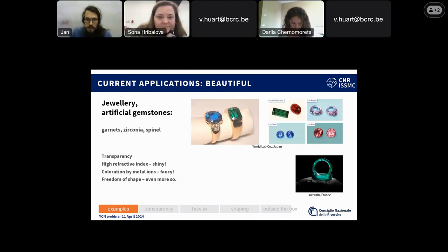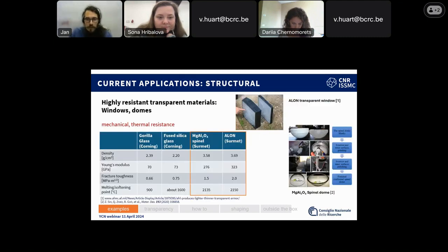And that's either you apply pressure, you become really, let's say, nasty on the material, and you, okay, that's not really scientific, but you squeeze the pores out. No, you just, by applying pressure, you really help the removal of the pores. Whether you use hot pressing, whether you use spark plasma sintering or hot isostatic pressing.